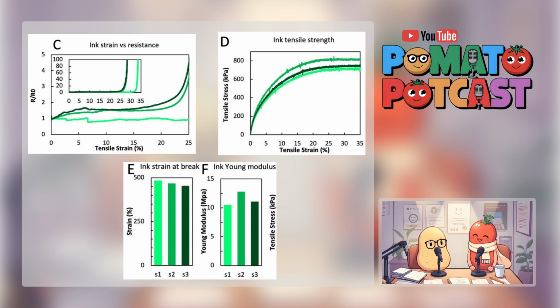Whoa. That's incredibly flexible. It really is. The Young's modulus, that's a measure of stiffness, is quite low, between 10.5 and 12.8 megapascals. Very soft and pliable. Does it bounce right back? There's a little bit of hysteresis, meaning when you stretch it and let it go, it doesn't immediately snap back perfectly. It takes a moment to recover, but it generally maintains its function within those strain limits.